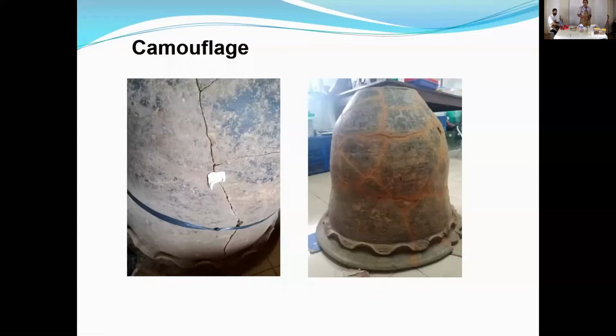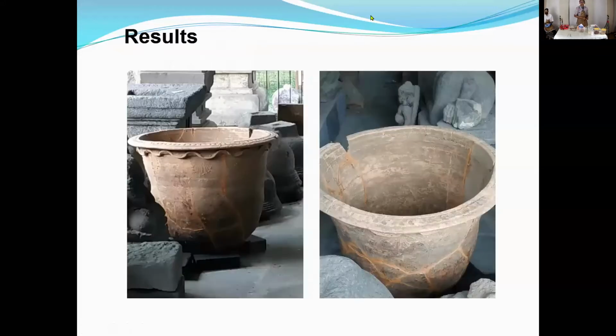This is the camouflage process that we did on the pot. We could see that there are cracks between the fragments. So to camouflage the cracks, we use a solution of anchor with a crushed terracotta material, brick material, and then we applied it on the pot. And that's the result that we get. As you can see, the result. Currently, the repaired terracotta pot is put in the space where we keep the heritage objects.